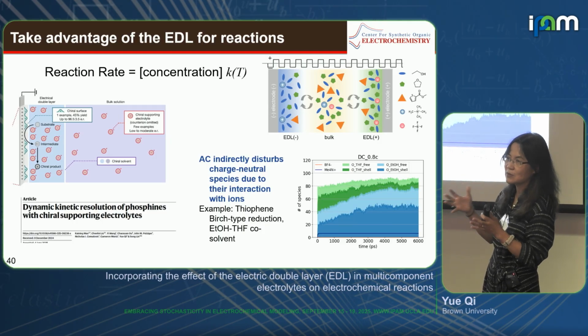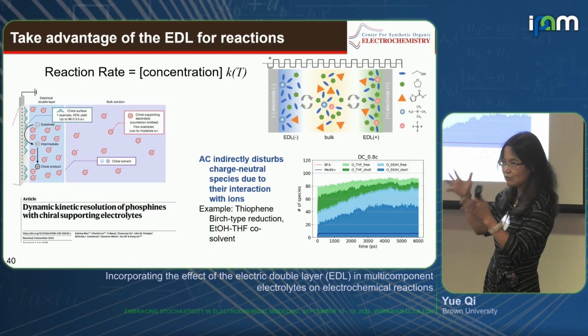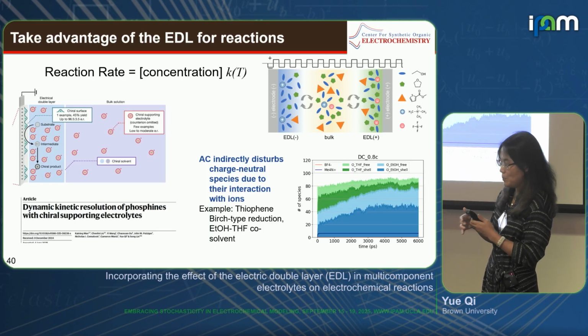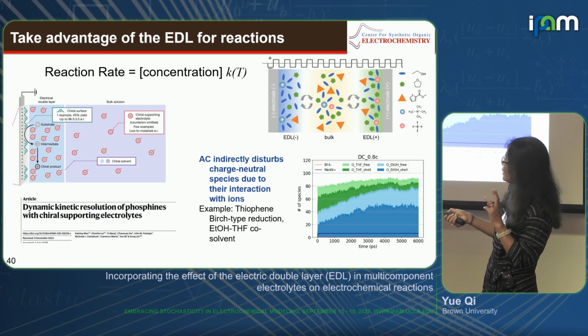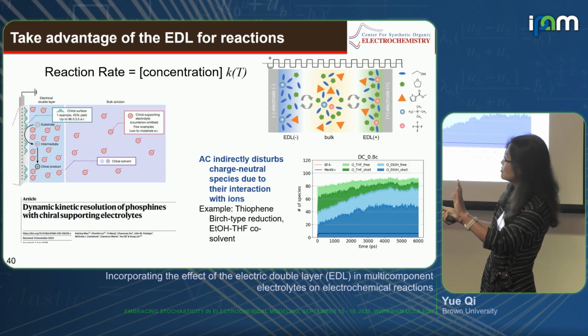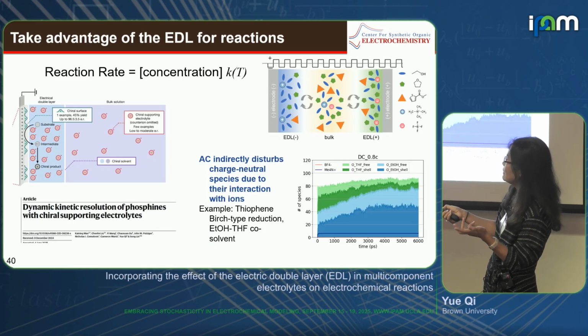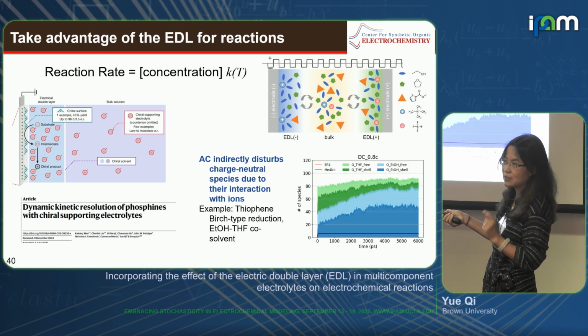If you're going to put those expensive molecules with chirality into the solvent, you need a lot of them. But if you make those chiral ions have a positively charged surface, those ions get higher concentrated near the interface, and they participate in this electrochemical reaction, and that can generate the chiral products. So they tried this strategy for a series of molecules they're interested in. Right? So anions and cations get redistributed. We can use those higher concentrations to achieve chemical selectivity.